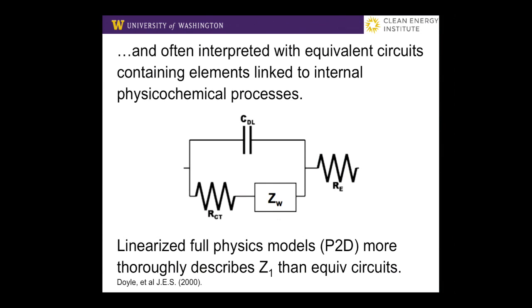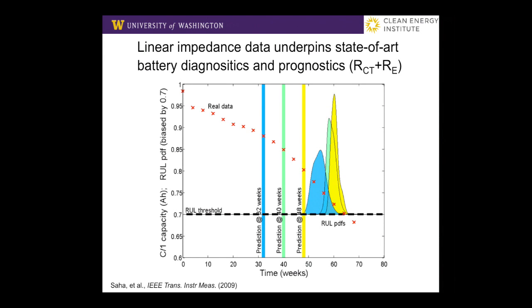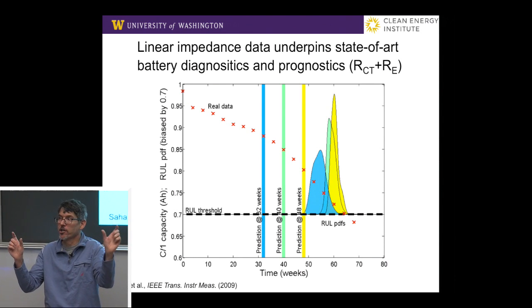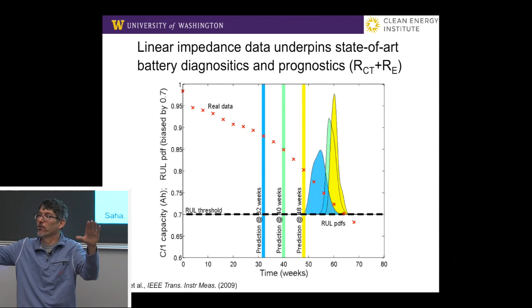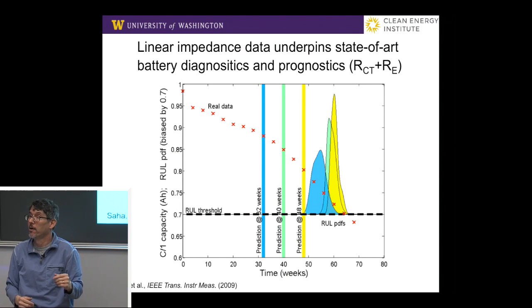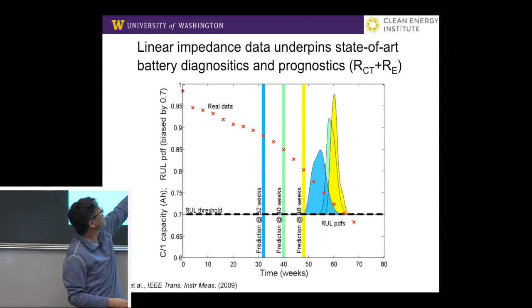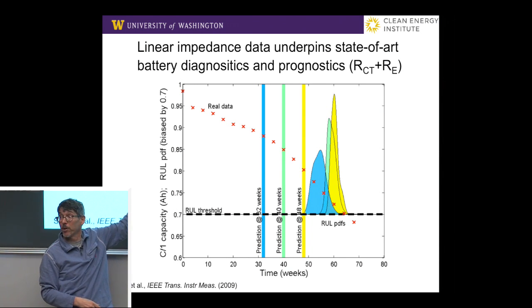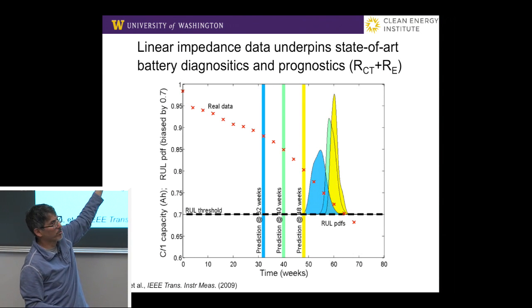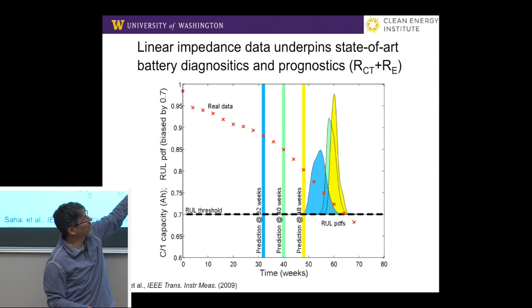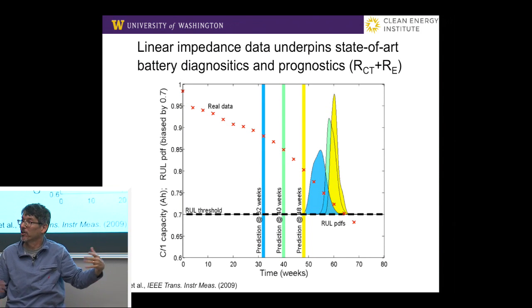But nonetheless, I want to show you that you can do interesting things with that small bit of extra information. Here, for instance, is an IEEE paper, a highly cited paper, because they're using a Bayesian framework to do predictions around measurements of this R charge transfer plus R electrolyte. So the sum of those two is a strong parameter for prediction. And this is showing the remaining usable lifetime. 70%, I said, is a typical number. And this was a long-term, DOE-funded study to look at the degradation of enough batteries that you could do statistics on it.